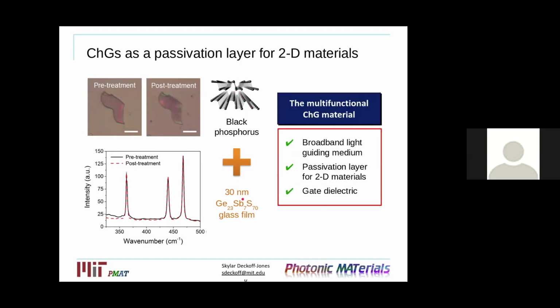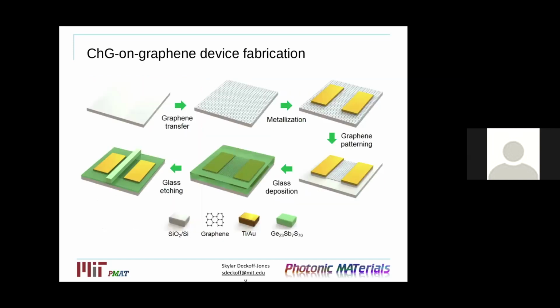So ultimately, the chalcogenide glass is a very appealing material, not only as a light guiding medium, but also for passivation as well as use as a gate dielectric. And to summarize our fabrication method, this schematic shows the method. As opposed to the method previously, where the final stage was depositing the 2D material, we start with the substrate with graphene, and we're then able to pattern electrodes, the graphene or 2D material itself, and then finally the waveguides.